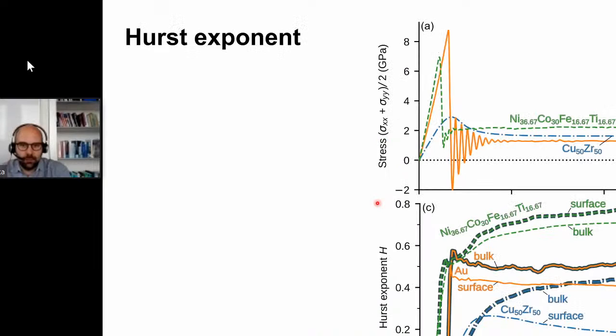Of course, we can extract the Hurst exponent from this analysis. What you see on the top right is stress as a function of strain. This is a stress-strain curve, and down here you see the Hurst exponent, now extracted from our surface analysis and our bulk analysis. They are very close for the high entropy alloy and the gold, and the high entropy alloy gives us something that is on the order of 0.7, what's often seen experimentally. I'll come back to the gold in a second.